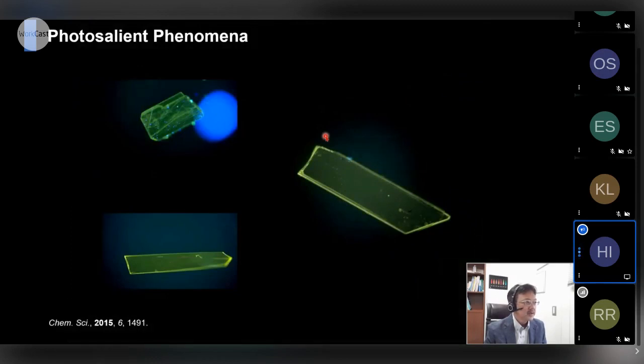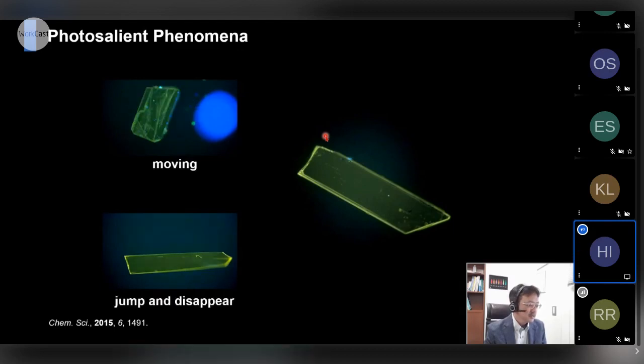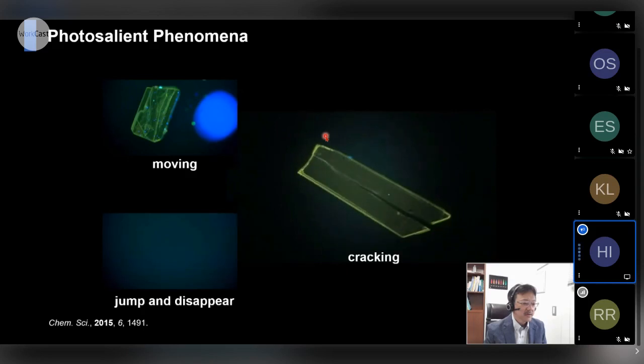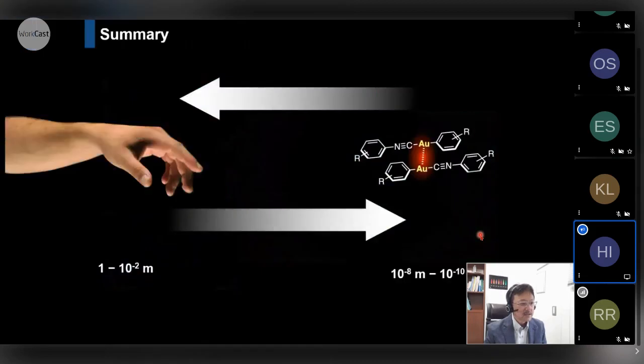So it is very difficult to see this phenomenon. Many times the crystals just move, or jump and disappear, or just crack. Maybe only less than 5% of compound crystals can jump, and more than 90% of the others just show cracking. So this is the final part.